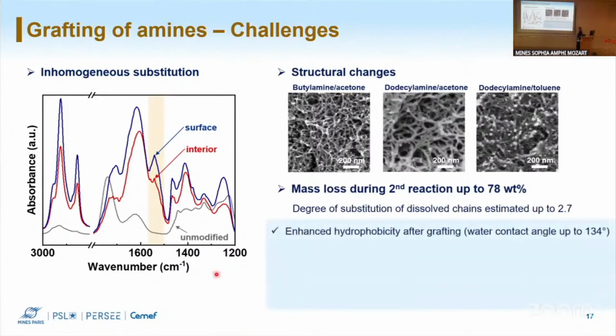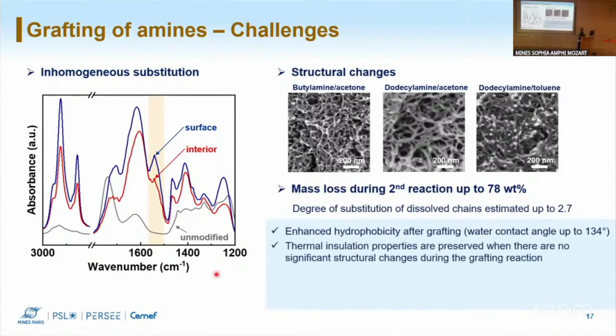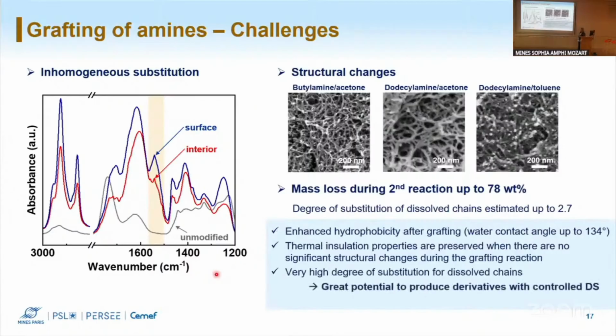So for these materials, in general, we could achieve enhanced hydrophobicity. We could reach very high contact angles, even with not as high degree of substitution. We could preserve the thermal conductivity of the structure if we had preservation of the network during the reaction. Then we could achieve a very high degree of substitution, but only for the dissolved chains. And it opens a very big door to produce derivatives of pectin with controlled degree of substitution.